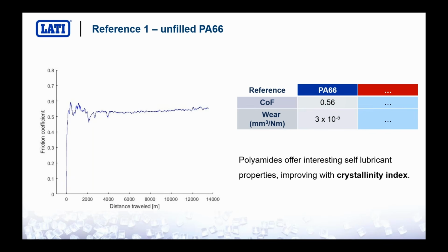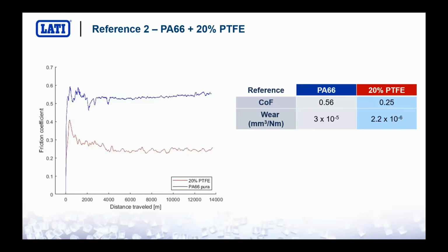Polyamide 66 is not one of the worst materials in terms of tribological properties, because it exhibits a very high crystallinity, and this is very helpful for the tribological properties. So this is the first reference, but the second reference was for sure the polyamide 66 plus PTFE. So our main reference, the goal to get closer.